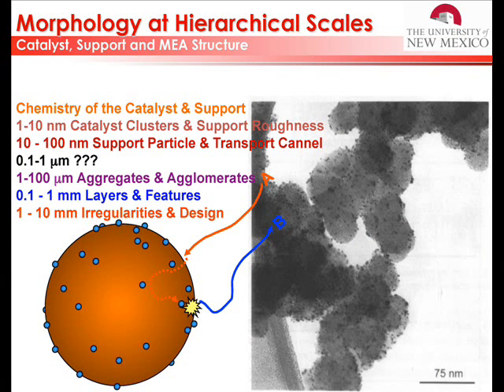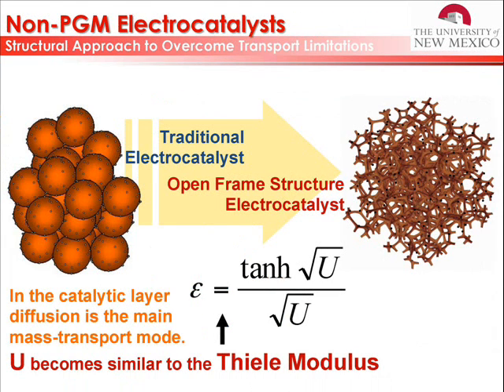We have a very small program about hydrogen oxidation because hydrogen oxidizes pretty well. And we do have comprehensive programs on reduction of oxygen. Over the last decade, a substantial paradigm shift was observed in the way we now understand the electroreduction of oxygen on non-platinum catalysts and electroreduction of oxygen on platinum catalysts. And this shift in the paradigm didn't only come with the increase of the turnover number or making catalysts better and better. It categorically postulated that the two types of catalysts are dramatically different by design.